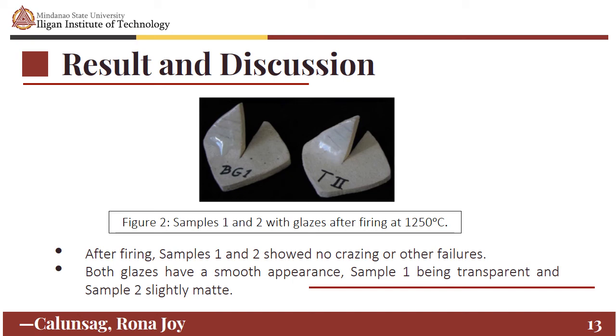The appearance of the glazes after firing can be observed in Figure 2, Sample 1, or the BG1, and Sample 2, which is the T2, fired at 1250 degrees Celsius, and in Figure 3, Sample 3 fired at 1100 degrees Celsius. After firing, Samples 1 and 2 showed no crazing or other failures, indicating that the thermal expansion coefficients of the substrate and the glazes are similar. Both glazes have a smooth appearance, with Sample 1 being transparent and Sample 2 slightly matte.